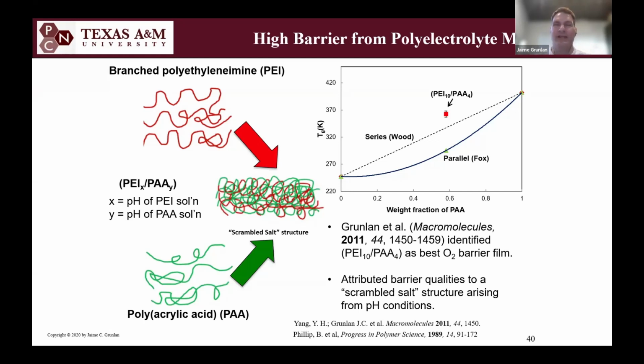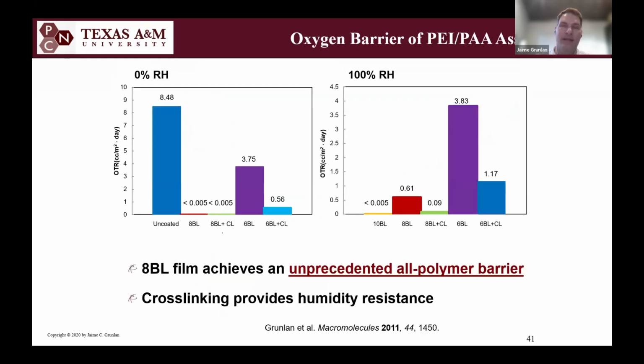And in this case, the glass transition temperature of those two polymers together is much, much higher than you would predict with the Wood equation, which is the upper bound of what you would expect the glass transition temperature to be. So we call it, I didn't invent this, somebody else, I think it's in this Progress in Polymer Science article, they termed this kind of idea a scrambled salt structure. It's two ionic molecules together, polymer.